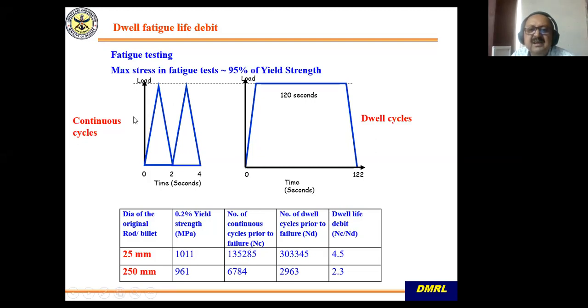That kind of cycle life is larger in this one because of the finer microstructure, and the dwell fatigue life is also larger in this as compared to this. I'm not going into too much detail, but this is basically because of micro texture. I will show you another example where I'll show micro texture. When you divide this by this, that is what is known as dwell fatigue life. You can see this is pretty high in this, but lower in this. This is primarily because of micro texture or texture which comes in, and it does affect the mechanical property. That is why I'm showing you here.